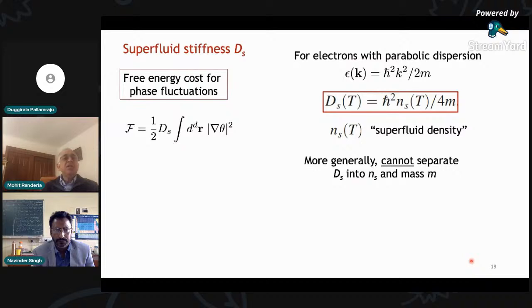Now, there is one terminology called the superfluid density, which is often used in the literature. So let me actually say what the relationship of that to the stiffness is, just so that those who might have heard of that will make a connection. So if I have electrons with a simple parabolic dispersion rather than some complicated band structure, k squared over 2m, then it turns out that the superfluid stiffness is just proportional to ns divided by m. Okay, where ns is often called the superfluid density.